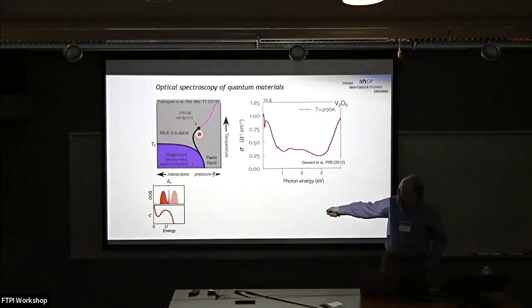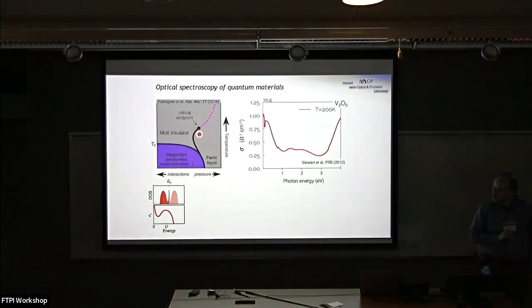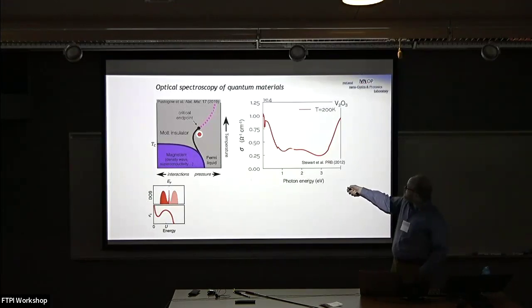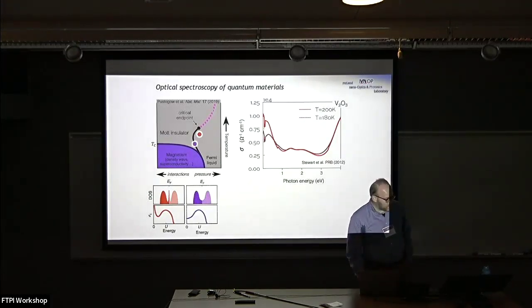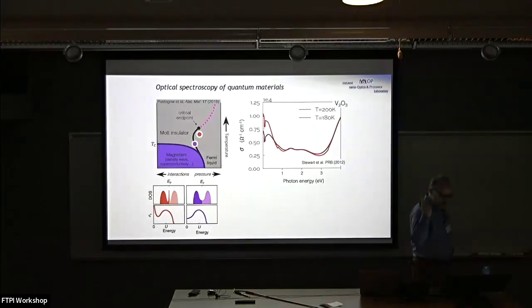So this isn't just a cartoon story. Taking some older data, traditional optical spectroscopy from my former colleague Maggie Stewart on that same material, V2O3, shows that a lot of these features show up in real spectroscopy data, notably the energetic feature out here at 1.5 eV. Now, if we cool this particular fellow down, we can navigate ourselves through this phase transition between Mott insulator and Fermi liquid. We lose a quasi-particle, and that is showcased in optical spectroscopy as well.